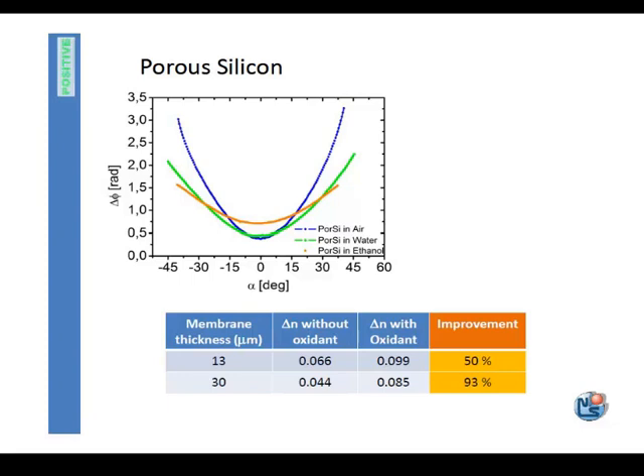Now here, I compare the optical birefringence between two different membranes, a thinner membrane, 13 micron thick, and a thicker membrane, which is 30 micron thick. In the first generation of samples, without the oxidant, we noticed a certain amount of birefringence, which was pretty high, but with the improved etchant composition, we are able to increase the birefringence value by 50% for the thinner membrane, and we are nearly doubling the birefringence value for the thicker membrane. We are now conducting experiments to measure the effective sensitivity of this new improved sample, and we expect to nearly double the sensitivity.